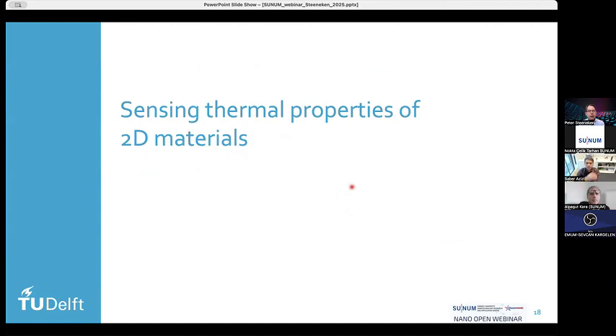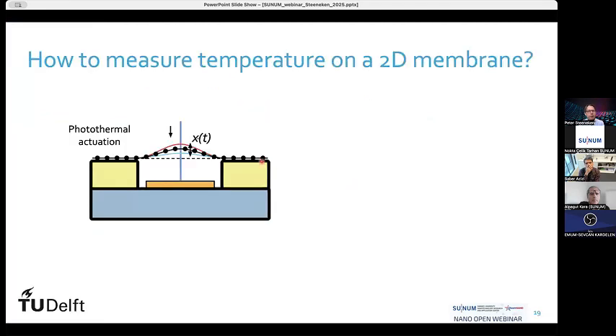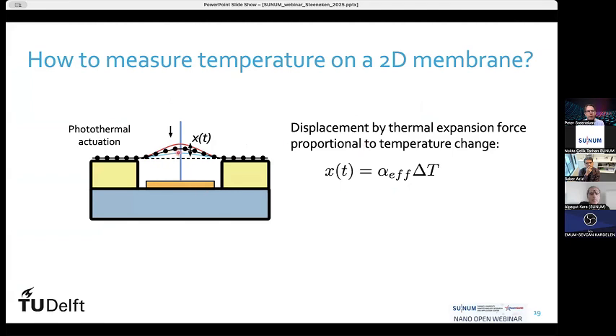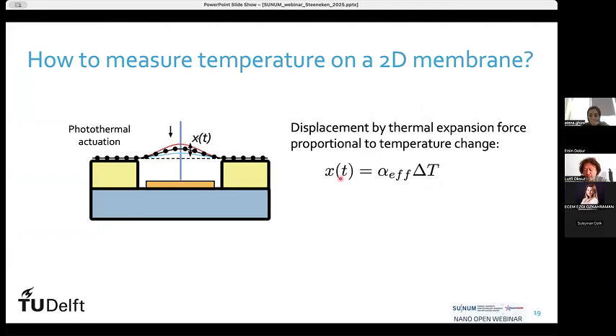Now I would like to turn to the thermal properties of these 2D materials. Like I said, we actuate them with a modulated blue laser, and that heats the membranes, but the heat also has to leave the membrane. We can use the thermal expansion coefficient as a kind of thermometer. How does it work? If you heat this material by an amount delta T, then by the thermal expansion coefficient, it moves a distance x, which is a linear relation.